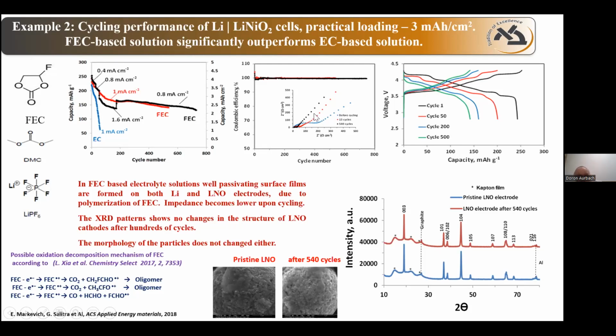And thanks to the unique surface chemistry that we have on both electrodes, we stabilize the situation. Interestingly, the impedance becomes smaller and smaller because of compactization of the surface film during cycling, and the cathode materials are untouched. If you take untreated material, you have cracked cathode material, the morphology is changed, but thanks to the unique surface chemistry, by XRD and by morphological studies, we demonstrate a very nice stabilization.